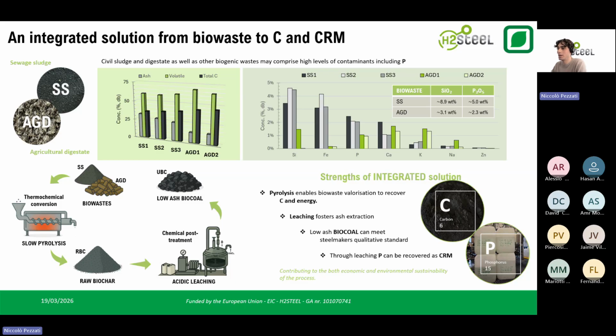And later, combining this first stage with a second post-treatment, which is supposed to remove those harmful elements, so the ashes, which concentrate after the thermochemical conversion. And this upgrading is carried out with the aid of an acidic leaching, which delivers a low ash biocoal eventually.